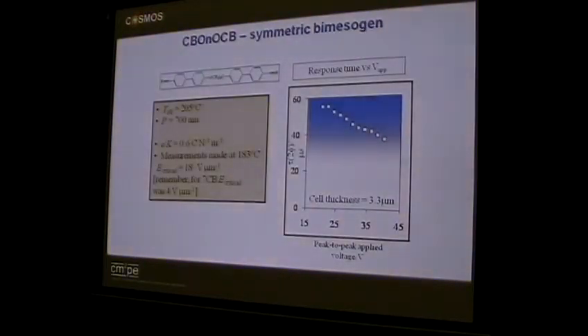So, just to prove to you that the system is fast, this is the first bimesogen response time in a nematic. I'm not talking about ferroelectrics, I'm talking about nematics. The response time is 40 to 60 microseconds. Okay, but the operating temperature is quite high. But it does show you all the things you need. The critical field for unwinding is very high, so you can operate your device quite happily between 0 and 10 volts per micron. Okay, so you have low delta epsilon, but you have a high temperature.